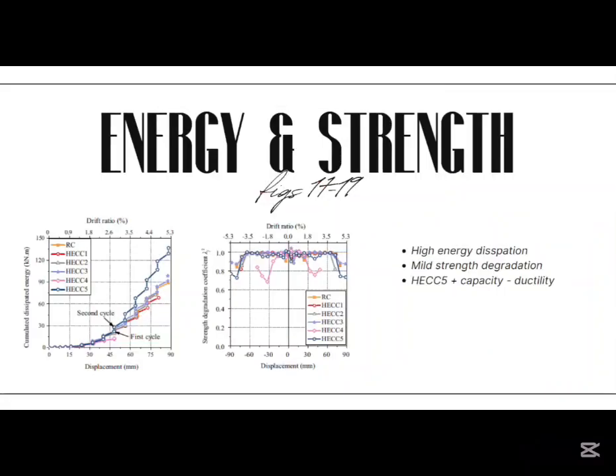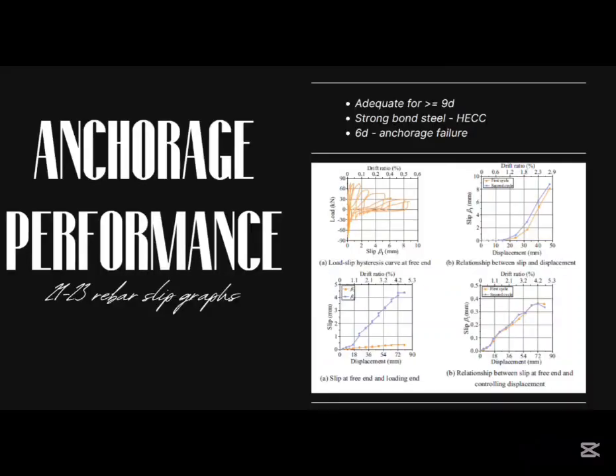The specimens could dissipate a large amount of energy during cyclic loading. Strength degradation was small for all of them. HECC 5, which had a higher steel ratio of 3%. Measurements of bar slip showed that an anchorage length of 9D was enough for good bond performance. Only the 6D specimen failed by pull out. This means that using HECC allows engineers to reduce the required anchorage length without losing safety.